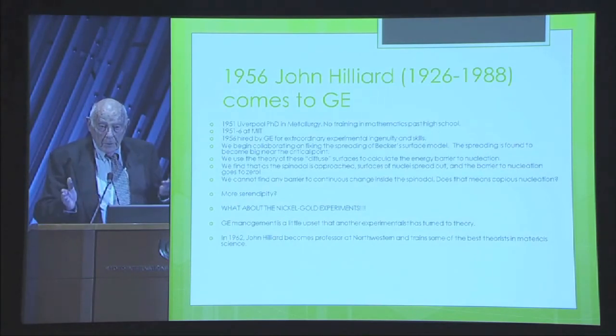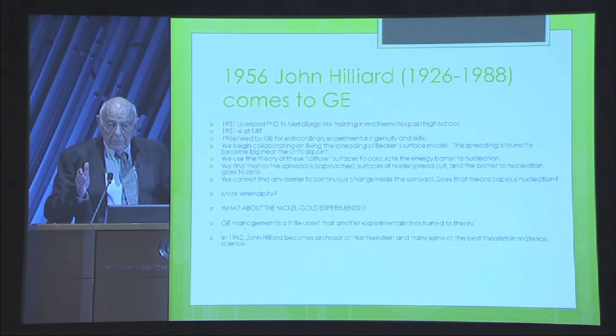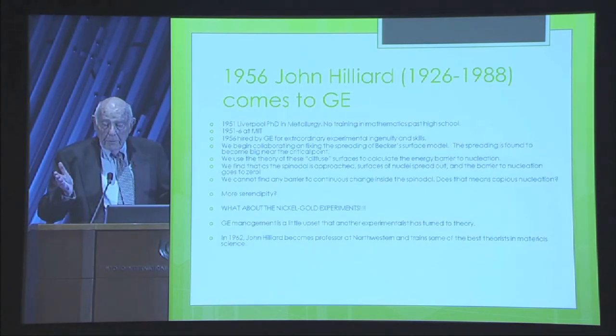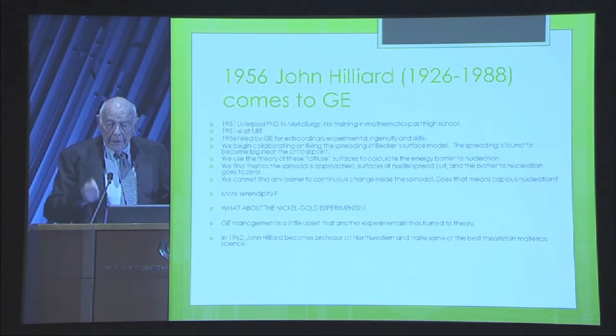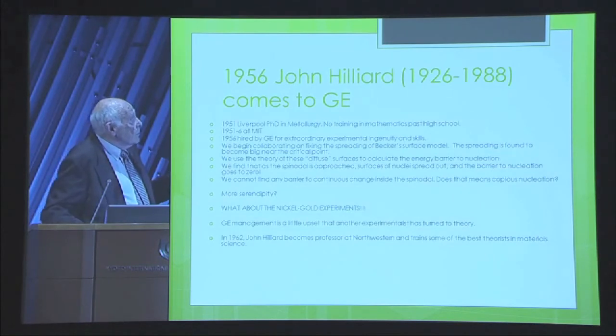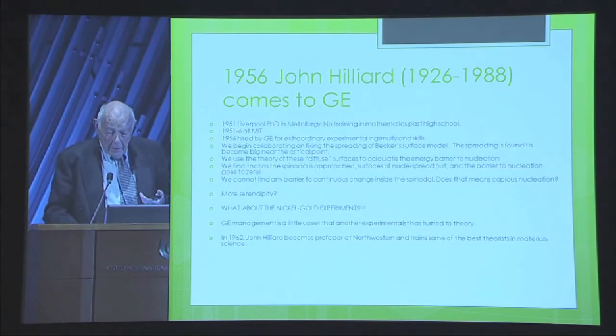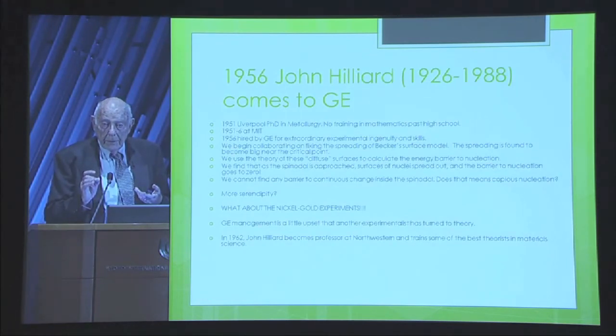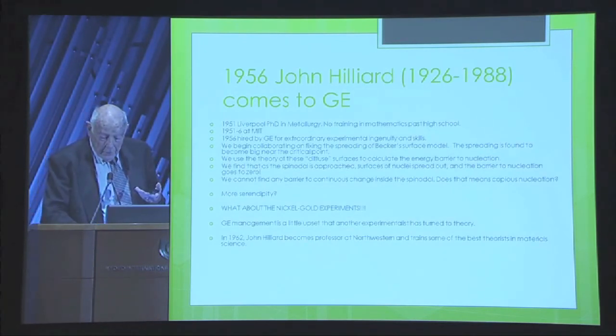So here something clearly was wrong. There should be no need to nucleate once you're inside the spinodal line. And yet, what about gold-nickel experiments? Well, gold and nickel atoms are 15% different in radius. So they are very different in size. And if you try to mix them on the same crystal lattice, there's a lot of strain. And this is something that was not part of the theory of the spinodal.